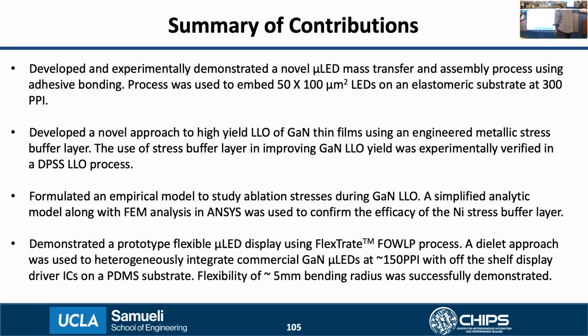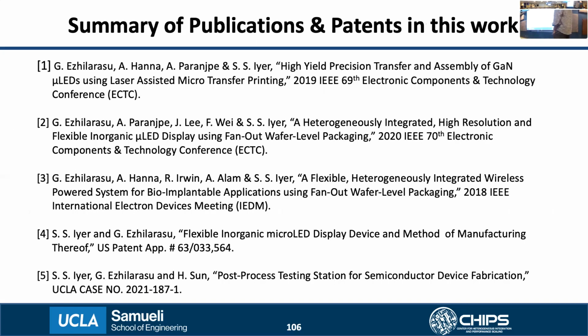I had also demonstrated a prototype flexible micro LED display using the FlexTrate platform, wherein a dielet approach was used to heterogeneously integrate commercial GaN micro LEDs at around 150 ppi resolution with off-the-shelf display driver ICs on a common PDMS substrate. Flexibility of about 5 millimeter bending was shown for this display. Here's a summary of some of the references and patents that were made in this research.